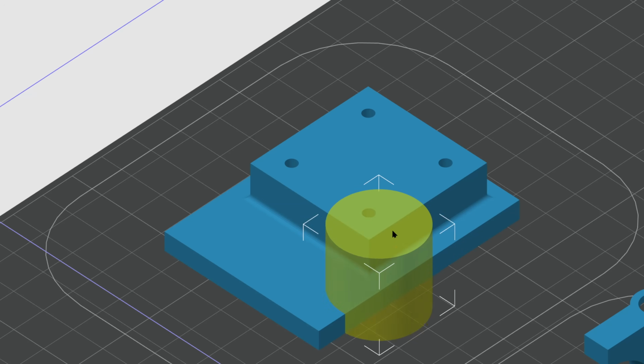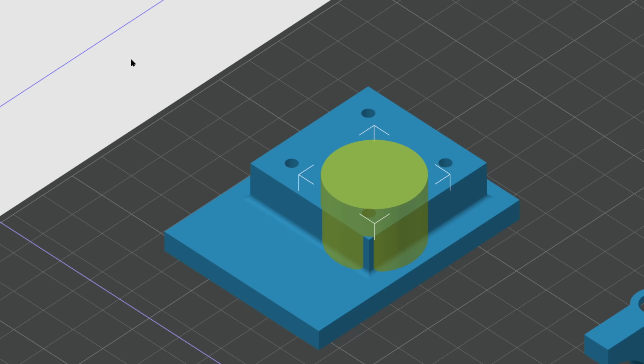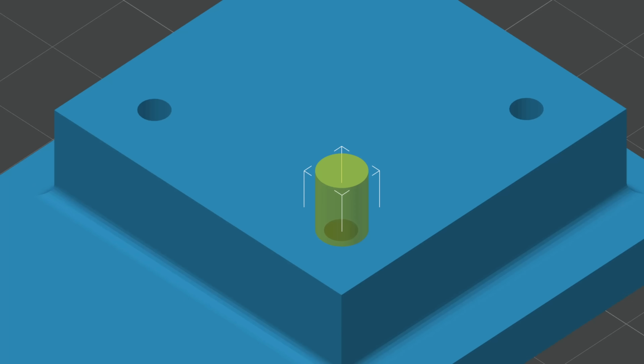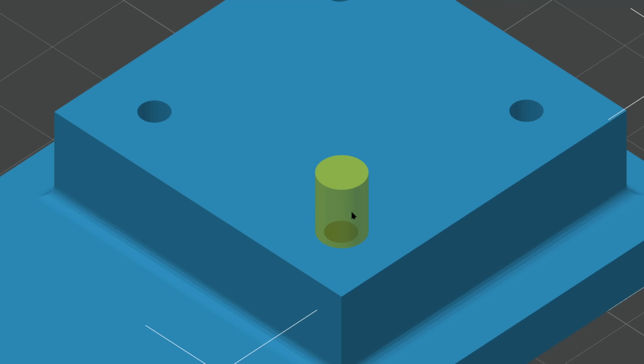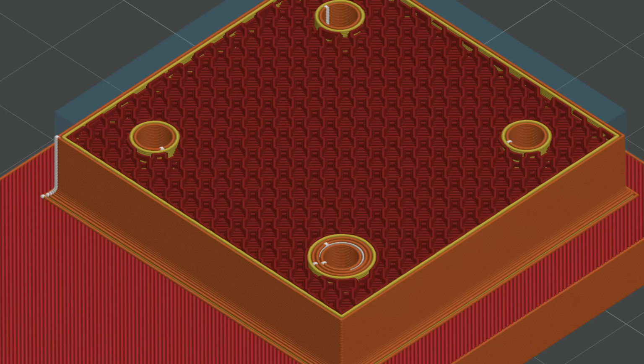The ideal number of walls is probably material dependent, but I recommend 4. 3 might work, but there's not a huge case for it. You can use modifiers in most cases if you want the holes to be 4 walls and the rest of the part to be different. Saves material, doesn't sacrifice strength.